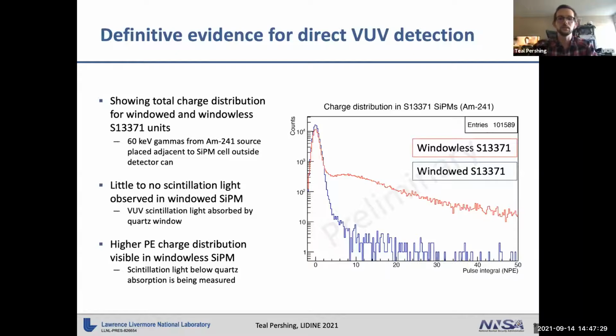And then from there, we did a comparison of the windowless to windowed S13371 units to see if we saw a difference, which would indicate that we're seeing the VUV scintillation component. On the right, the blue curve is the total pulse integral from -1 to 11 microseconds centered around the trigger, to try and collect the entirety of the americium-241 gammas. You can see the windowed unit sees very little light. For the most part, you're just seeing 0 to 1 PE pulses, maybe a little bit more. And then in the windowless unit, we see a clear second distribution in a higher PE space, which we expect is due to the americium-241 gamma.